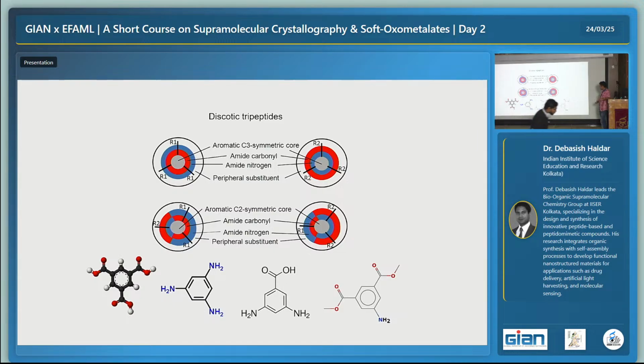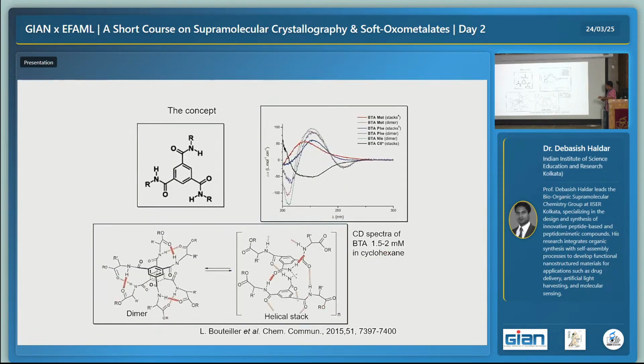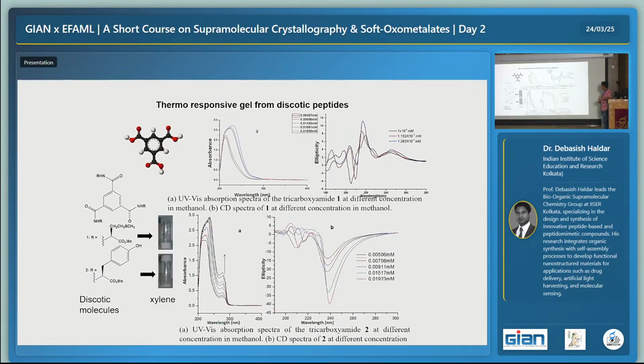So what is happening with this C3 symmetry? How is this compound behaving with change of symmetry? There is some literature from the Bouteiller group. They prepared this kind of compound and studied extensively using CD, and they proposed that one and so forth. So we have developed this compound with this benzene tricarboxylic acid, and we have replaced the acid to make an amide either with methionine or tyrosine.